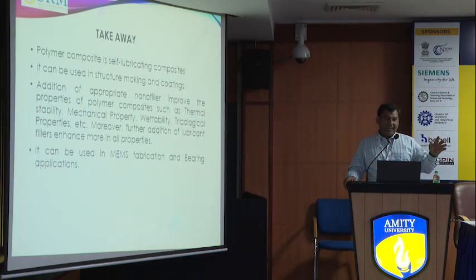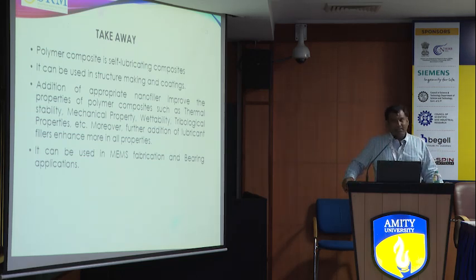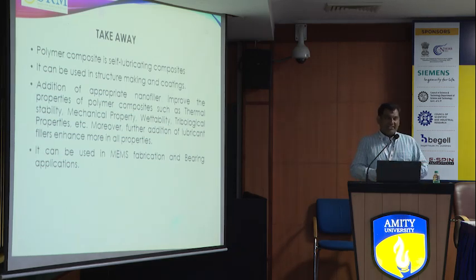They are developing a nanocomposite paint which can show antibacterial, anti-friction, anti-wear and anti-corrosion properties, because these three things are very important for any automotive. And that succeeded also, because one BTech group did it, and it became a startup on that particular base. They tested five bacteria available in our biotechnology lab, and it succeeded: even after 24 hours the bacteria did not harm anything in the coating. After striking the bacteria, we kept it for 24 or 48 hours, which is sufficient time. If any reaction is there, we can observe it through the microscope. So that nanocomposite paint was developed, and it was good work.